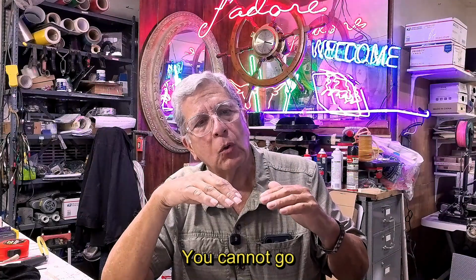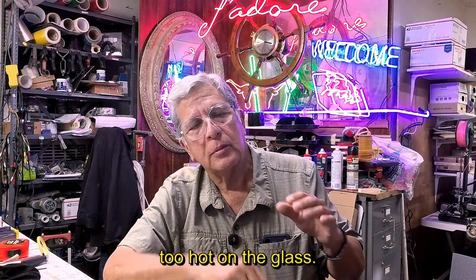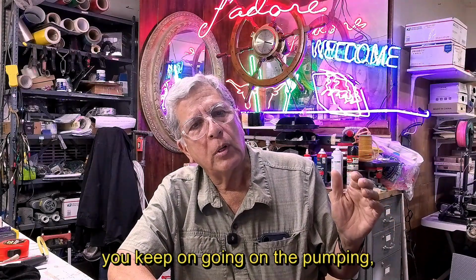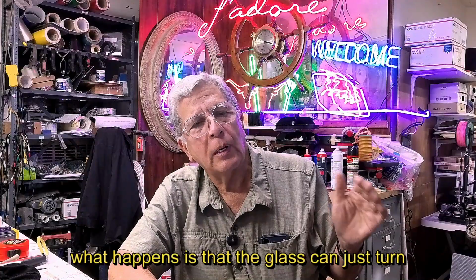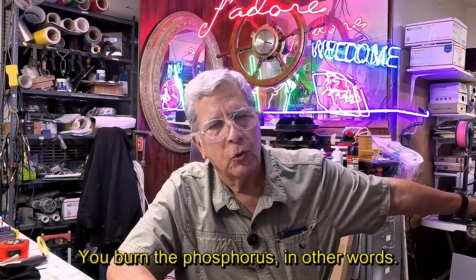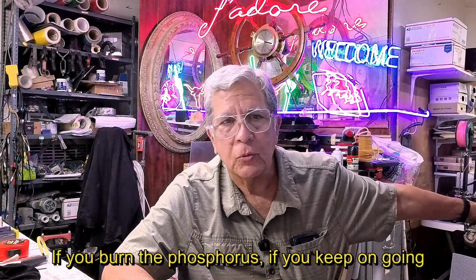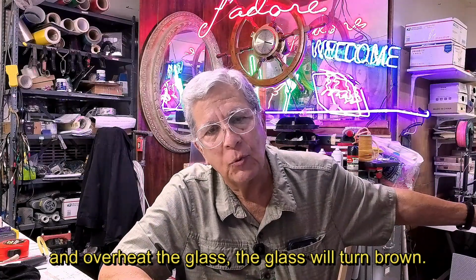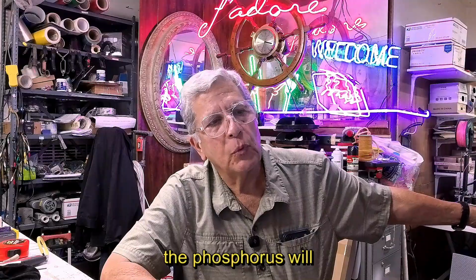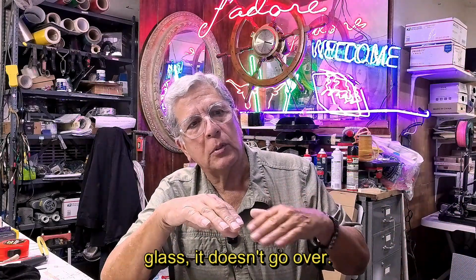You cannot go too hot on the glass. If you keep on going on the pumping, what happens is that the glass can just turn brown. You burn the phosphorus, in other words. If you keep on going and overheat, the glass will turn brown. The phosphorus will not work anymore, and you've destroyed the glass. So you have to be careful that the temperature of the glass doesn't go over.